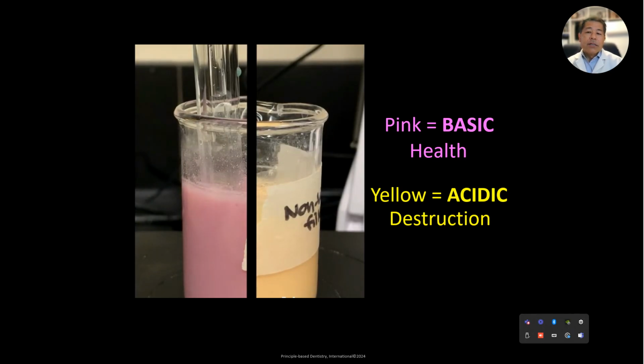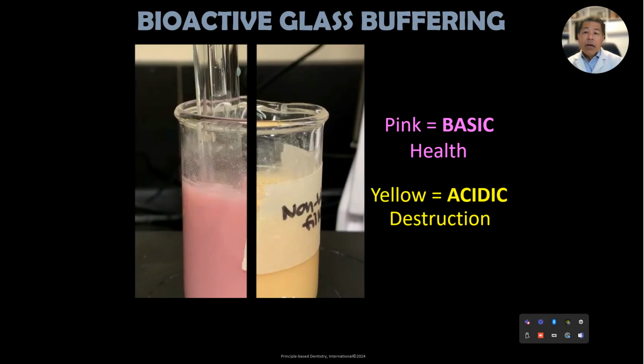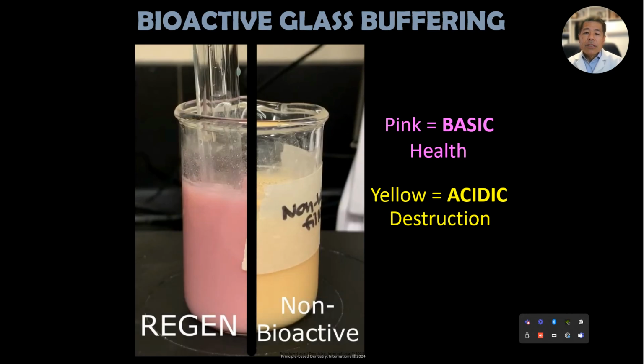So what they'll do again is introduce an acid, and as they introduce the acid again, the right side stays yellow. The left side turns pink. It's neutralizing the acidity. So how does it do that? Well, the bioactive glass is buffering out the acidity. On the right hand side, we just have normal fillers that you'd find in a conventional composite restorative material. On the left hand side, you see Regen, which is a restorative composite material that has the Bioglass 45S5 in it. So the filler material, partially being Bioglass 45S5, is neutralizing the acidity.